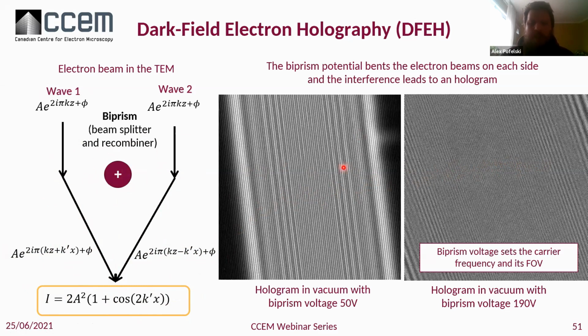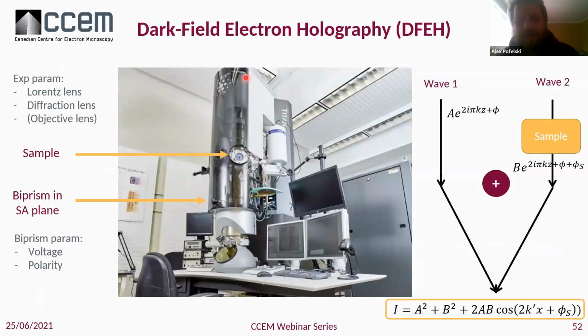So by changing the potential of the biprism, you change the field of view and also the fringe spacing, you change the carrier frequency, this K prime, depending on what you want to do. So this is the way of expanding the field of view of your hologram. So how to do this? Technically, this is the image of the Titan Lowbase. This is where you put your sample in. The biprism is located here in the SA plane. So what you have access to in the biprism is the voltage and the polarity. You can change to negatively charged, and this will also work.